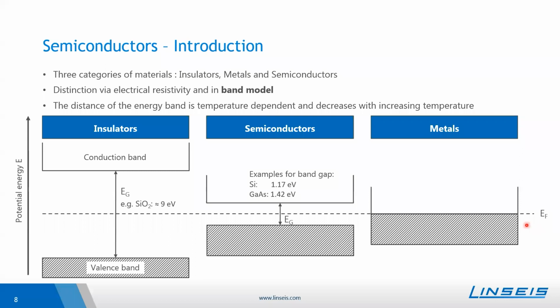Also, so that you have a feeling for what is a large gap, and which gap is small enough to be overcome: a band gap of about 3 electron volts can still be overcome by excitation. Some well-known examples: silicon has a band gap of about 1.2 electron volts, gallium arsenide has about 1.4 electron volts, and the insulator silicon dioxide has a band gap of about 9 electron volts. Furthermore, it is important to know that this distance of the energy bands is temperature dependent, so that the band gap typically decreases with increasing temperature.